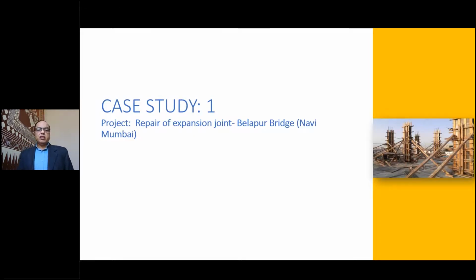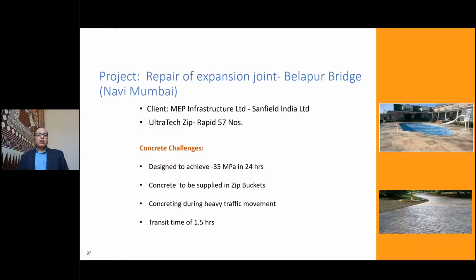Repair of the expansion joint at the Belapur bridge. You know, Mumbai, Navi Mumbai, Belapur is a very busy junction, and the bridge had to be repaired, and the quantity of concrete required is small, but the quality requirement was very high. In the sense, you can't close that road for several days. You can't say I am using concrete, therefore wait for 28 days, wait for 7 days. No, that is not possible. Therefore, in this case for the Belapur bridge, the challenge was to achieve 35 MPa of concrete in 24 hours. Not even in 3 days, in one day you have to achieve 35 Newton per millimeter square.